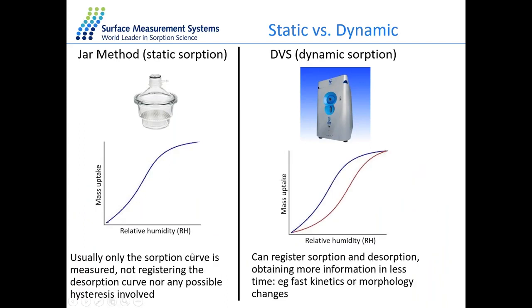Also, with the jar method, the only thing we can really obtain is a sorption curve. And we can't really obtain the desorption curve and look at any hysteresis involved. Whereas in the DVS, we can measure sorption and desorption. And so we have more information about our sample, especially in regards to kinetics and morphology changes by looking at the hysteresis gap.